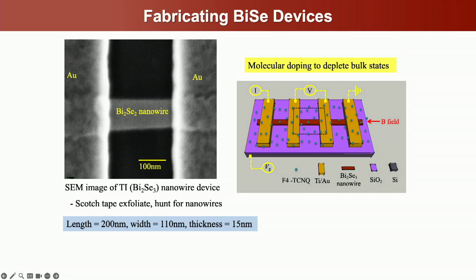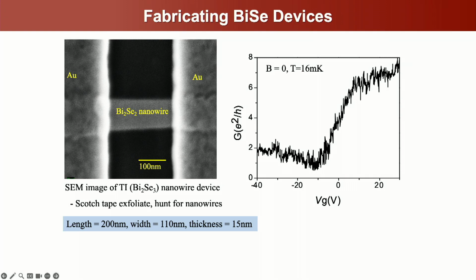And then we measure conductance on here. You can see we get really nice conductance that gets us through the Dirac point, and also relatively high conductance for this sort of system. If you've worked with graphene nanowires, as you make them to the scale of 100 or 200 nanometers, the resistance increases tremendously. And so already with these topological materials, you can see that even when you make it pretty narrow, about 100 nanometers, the conductance stays around e squared over h, which is relatively high. So there's somehow just less edge and boundary scattering in these systems than you get with other comparable systems.